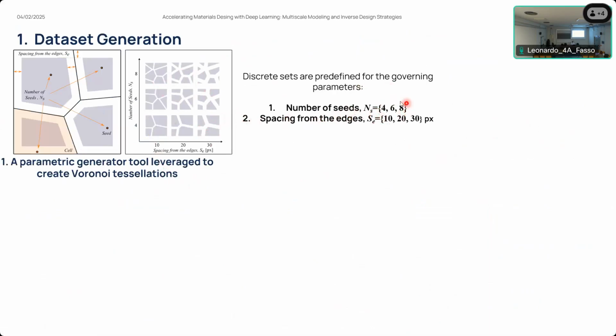So specific values of 4, 6, and 8 are assigned to the parameter associated to the number of cells, and specific constant values of 10, 20, and 30 pixels are given for the thickness of the grain boundary. This is important because when we analyze the kind of images that the GAN, the Generative Adversarial Network, is able to generate, we will understand that this deep learning model is also able to incorporate new features completely different from the ones that we used to train it. So we say that it's able to extrapolate, and this will confer important properties in order to target other points in the material property space, not characterized by the training data.